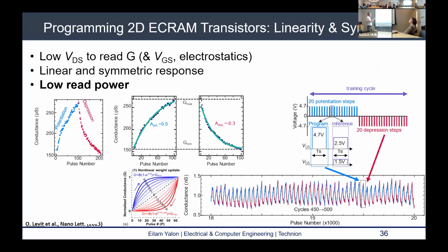So this is a demonstration of the conductance versus number of pulses, or potentiation and depression pulses. This is a single cycle. And we can extract nonlinearity coefficients of 0.5 and 0.3. We want below 1, so these are pretty decent linearity numbers. And the asymmetry is also pretty good, 0.1 and minus 0.3 for the potentiation and the depression pulses. These are some other merits that you can find. One thing to note is that because it acts as a transistor, during the readout we apply gate voltage. That's an advantage and a disadvantage. The advantage is that the off-state leakage is lower, but the disadvantage is that we need to apply gate voltage during the readout.